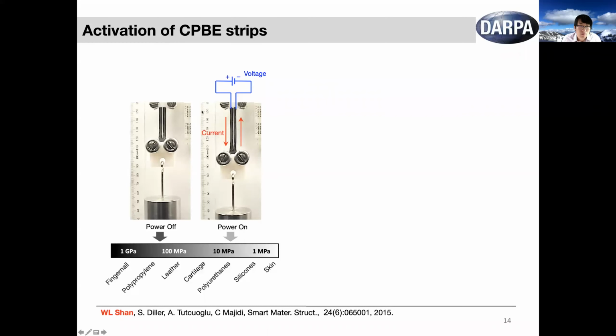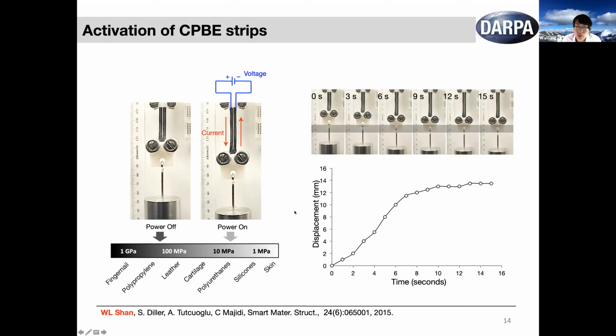As you can see, after we apply some voltage, the stiffness, or the Young's modulus, of the structure will change from over 100 megapascal to roughly a few megapascal, which is more than 30 times stiffness change. And we can also characterize the activation time that's needed for this change. You can see that roughly in 10 seconds, we will be able to complete the activation if we use tens of volts as activation voltage.